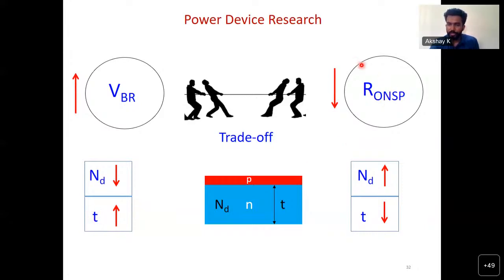But on the other hand, if you want to reduce the on resistance, you need to have high doping and low thickness. So basically what I mean to say is that the requirement is contradicting. Here you want lower doping, here you want higher doping, here you want higher thickness, here you want lower thickness. So this choice of these parameters is contradicting. That's why we have this trade-off between these two parameters.